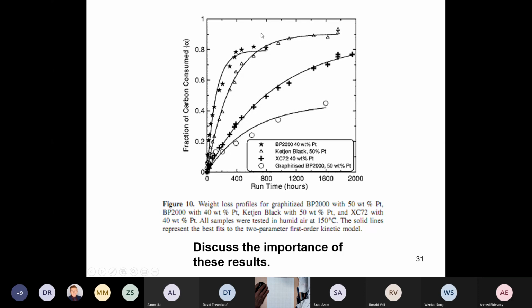Yeah, so then what we did was we said, okay, why are these corrosion rates so rapid? And one of the things about carbon of a small size is that the surface of the carbon has unsatisfied bonds. You've got surface functional groups there, like carboxyl, C double bond O, all kinds of different things. And what we were thinking is that these carbon atoms that are in an unsatisfied bonding condition are more prone to reacting with oxygen in the presence of the catalyst.